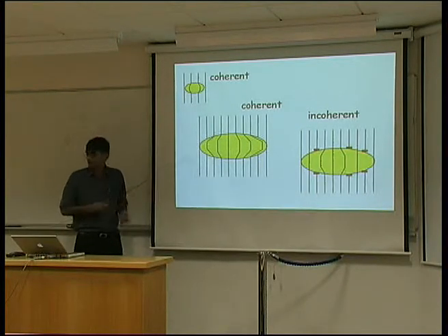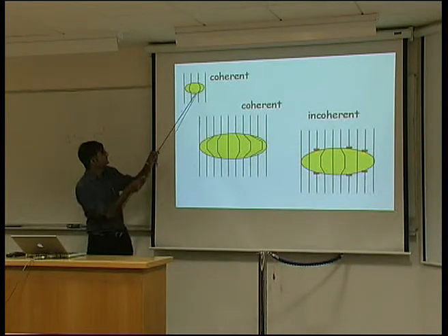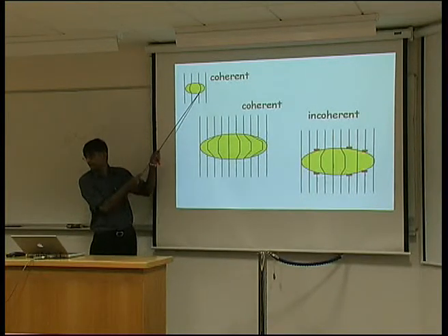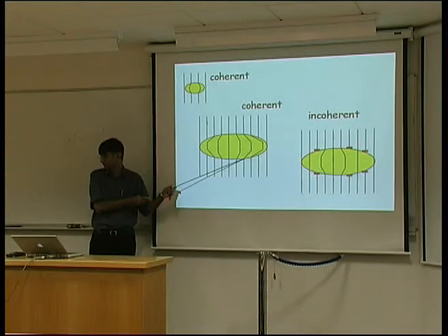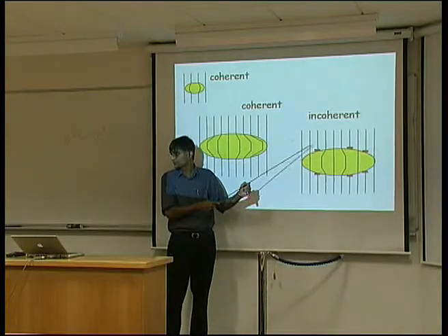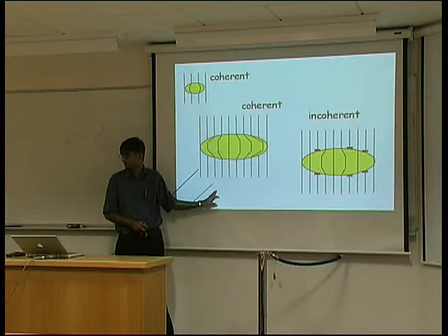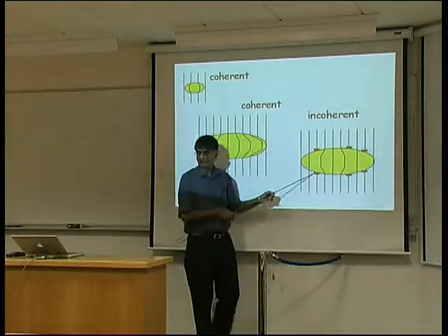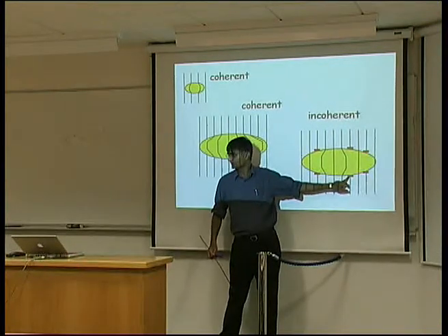And that's okay to bend those planes when the particle is small, because you can see that when the particle is small, these displacements are smaller. And they become more severe as the particle grows, until you get a breakdown of what we call coherency. Coherency means there's continuity of lattice planes across the boundary. So this would have a high interfacial energy because look, there are defects here, which have dislocations.